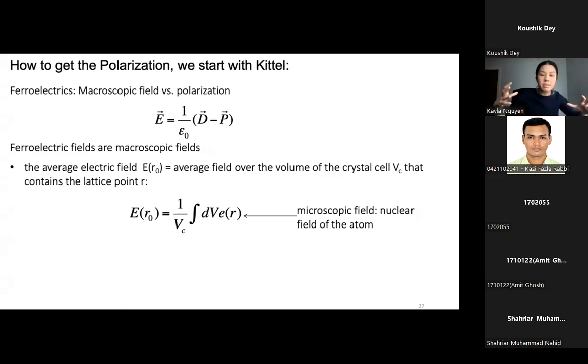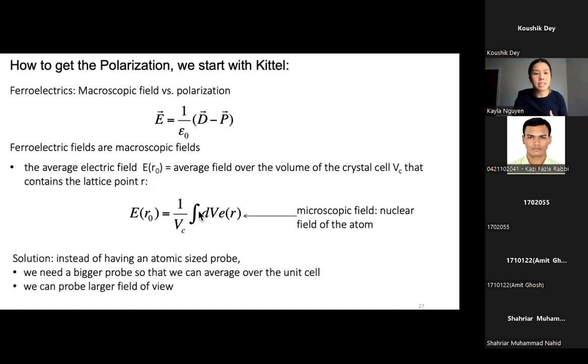The unit cell size of strontium titanate and lead titanate is around 4 angstroms. And so for us, what we need to do is make our probe about 5 to 7 angstroms so that we're averaging over the unit cell. So we're getting this macroscopic ferroelectric field. This equation tells us that in order to get back this ferroelectric field, we need to use a large probe that averages over the unit cell size. Instead of having an atomic size probe, we need a bigger probe where we can average over the unit cell and we can get a larger field of view.